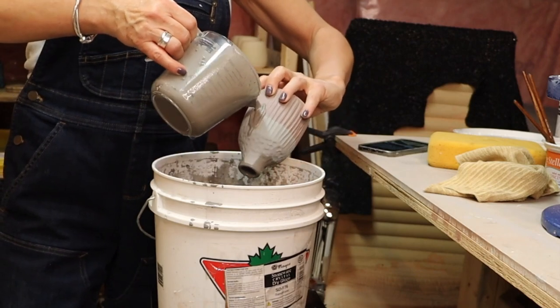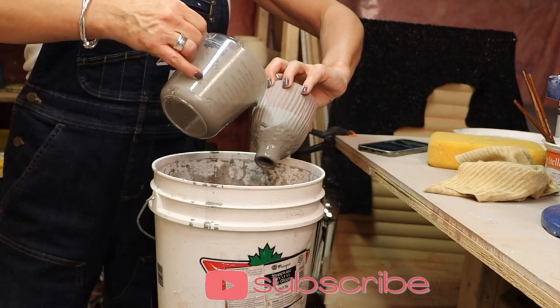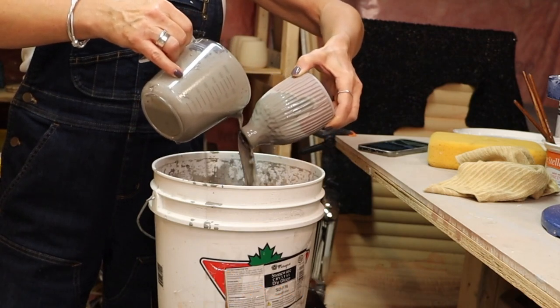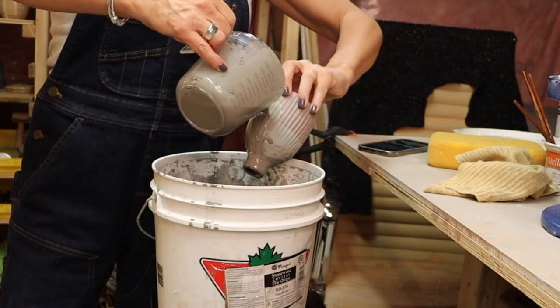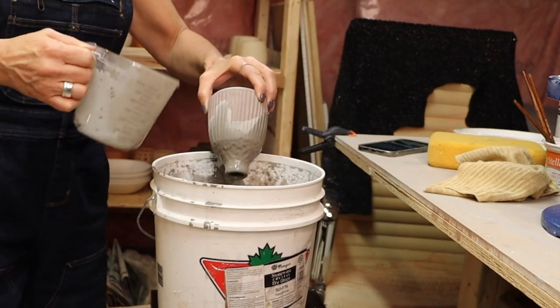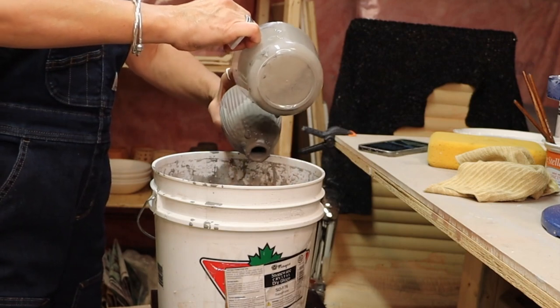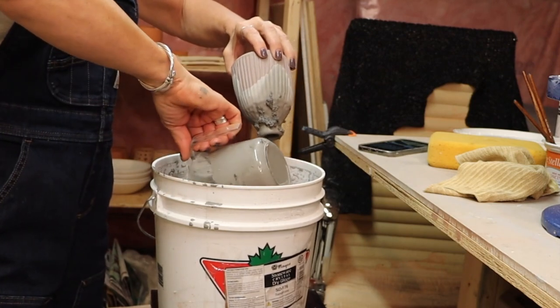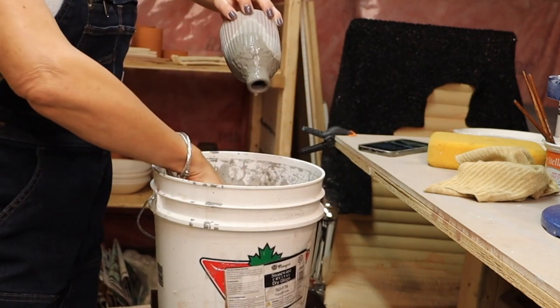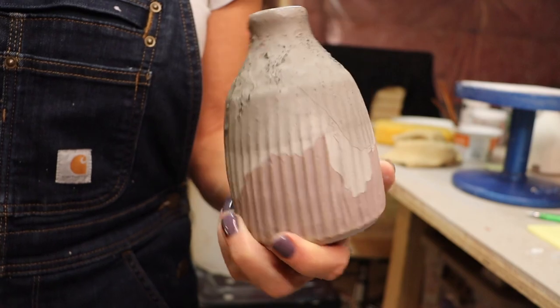I am pouring it. I find that with this particular glaze, you want to make sure you get the crystals sort of dispersed nicely. How I do that is by pouring the glaze over and then just trying to get the base part of the glaze on where I want it. Then I kind of hold back some of the crystals. You can see all those crystals and I will sprinkle them on — I know it looks like a lot, and if I left it this way it would be a disaster. I then just kind of pour back some of the crystals, pour them off, and then you're left with just the perfect amount where you want them so that you get your desired effect.